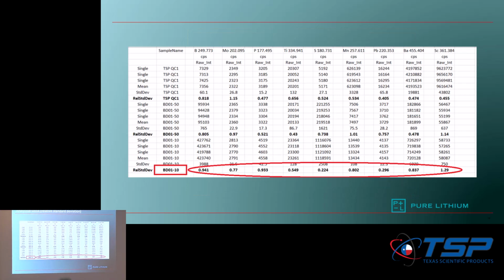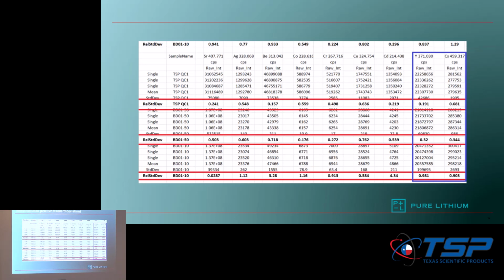So, a quick look at some precision data. The relative standard deviation here is typically under 1%, anywhere from, I'd say, 0.5 to 0.7 typically. Here you'll see both certified reference materials, which is the QC1, and real oil field brines below. You can see there's only a small degradation if we look at the beryllium, from 0.1 to 0.7 on the following sample. On the chrome, which is one we look at closely, it stays consistent.